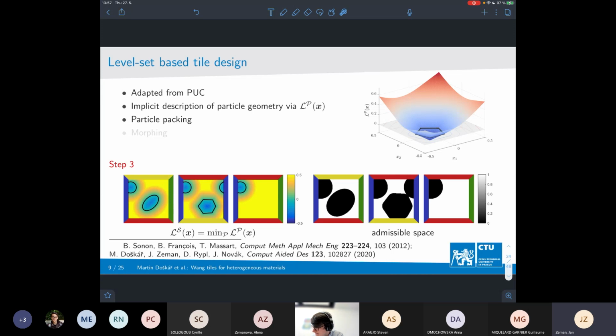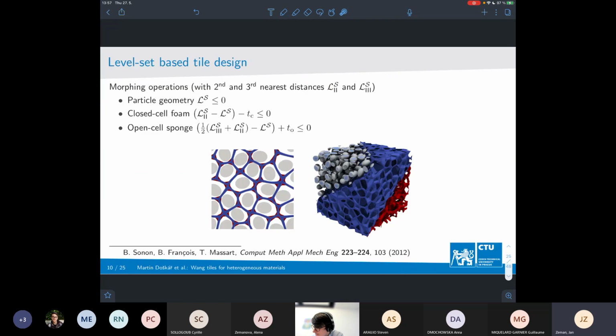So once we place enough particles in our system, we get the corresponding level set. And we come to the second step, which is morphing. And this can be either relatively straightforward or a bit elaborate, but still very computationally efficient. So for instance, if we look at the points for which the level set is non-positive, we are able to generate particles. So from this representation, we are able to get these spherical inclusions in 2D and of course in 3D using exactly the same manner.